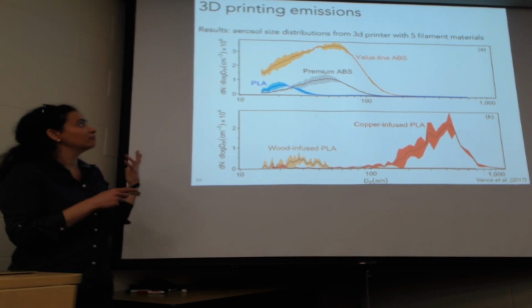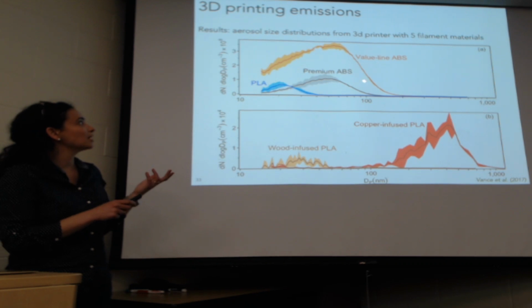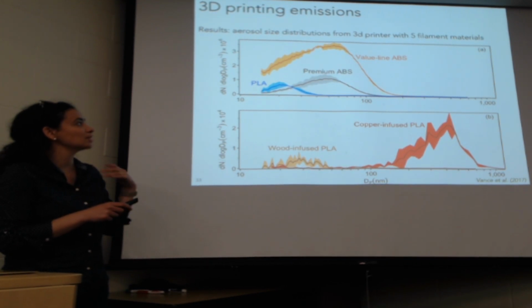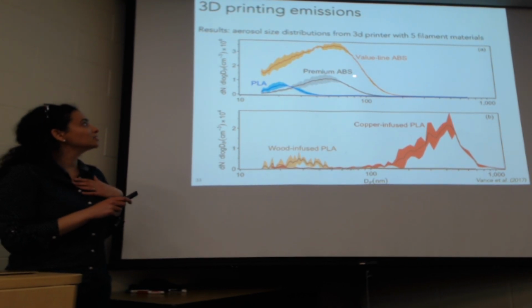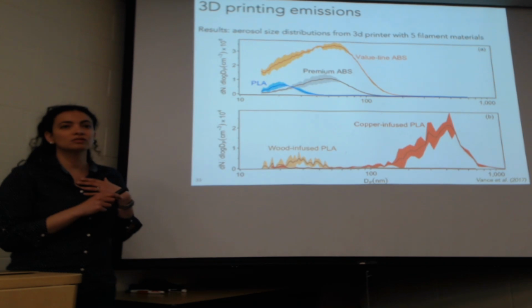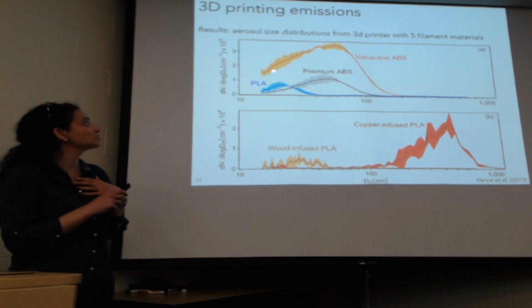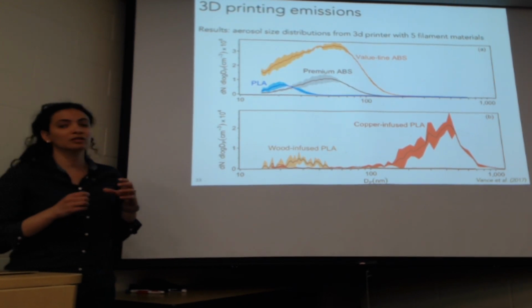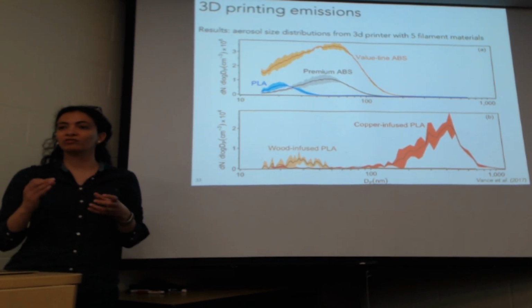So again, the value line, the cheaper ABS, had the highest concentrations, highest emissions as well. And the particles were about 50 nanometers in size, so fairly small, of course. The premium ABS had exactly the same mode. So the particles looked about the same, but there were fewer of them.